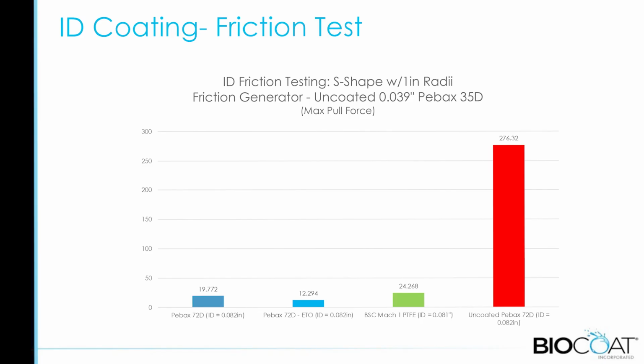But for instance, in one test we did where we have sort of an S-shaped curve where we're running a tubing through there, we were getting with an uncoated PEBAX about 270 grams of force, and it was really tough to push that through there. In comparison, a Teflon lined device of that same diameter would be down at around that 25 gram level. So like a 90% reduction from there.